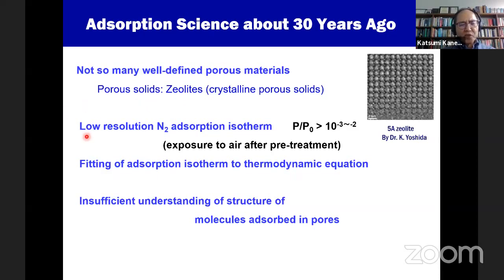And also adsorption measurements were not so good because low-resolution nitrogen adsorption isotherms were measured, with the minimum relative pressure starting from 10 to the minus 3 or 10 to the minus 2. Even so, often they must pretreat in vacuum, but they must expose to the air. So it was not an idealistic measurement. And also at that time, there were no personal computers, at best just a fitting of the adsorption isotherm to thermodynamic equations. A very great limitation. In particular, there was almost no understanding of the structure of the molecules adsorbed in pores.